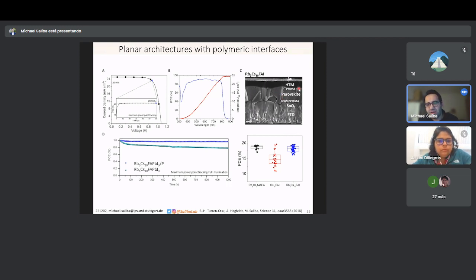It required us to use PMMA and PCBM PMMA as a passivation at both top and bottom interface. And they were necessary both for performance reasons in order to avoid pinholes, here, for example, many pinholes, but also for stability reasons ultimately as well. And beautifully, it also confirmed here that we had high currents towards 25 milliamps. And nowadays, it's nearly 26 milliamps per square centimeter using pure FAPbI3 with similar approaches to what we've presented here.